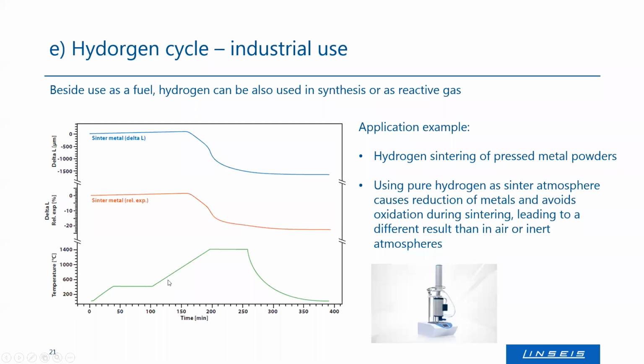You heat them up with a certain speed, and then you get to a target temperature that can be specified depending on the material. And then you hold the temperature until the plateau of shrinkage is reached. That means the sinter process is over when the plateau is reached and the sample is no longer changing its dimensions. Once this is achieved, you can start a defined cooling or ballistic cooling process. And during cooling, of course, your final ceramic will shrink naturally as every material shrinks when cooled. And this is a typical sinter process. In that case, it was a hydrogen sinter process of some catalyst materials, which we are frequently doing where we are already involved. Therefore, we have a special dilatometer that works under hydrogen atmosphere.